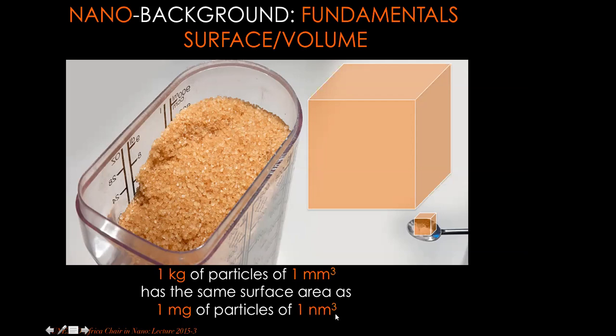You would understand that if I have to use platinum or diamond, for example, instead of taking 1 kilogram of platinum of 1 millimeter cube, I should take 1 milligram. I have to take these small particles and divide them in a way to have grains of 1 nanometer cube particles of platinum. And therefore, to have the same surface as 1 kilogram, I would have only 1 milligram. Therefore, it will cost me less. But the point is that the surface area is huge at the nanometric scale.